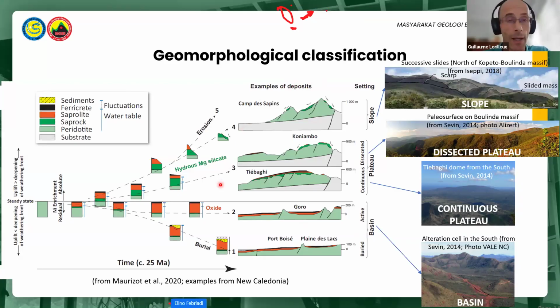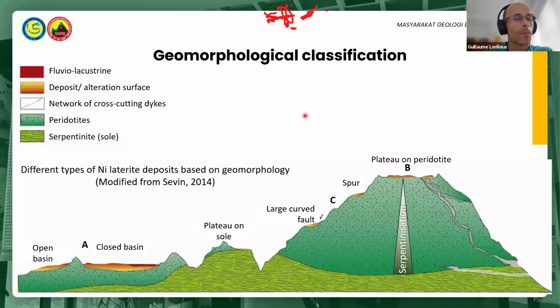The plateau deposits are topographically inverted former basins. Uplift increases from continuous plateau to the slope deposits. As the level of uplift increases, erosion also increases, leading to truncated laterite sequences and thinner limonite relative to saprolite. The importance of slope ruptures increases in dissected plateau and slope types and is associated with the development of deposits on the flanks of the massif. This is a different illustration of the geomorphological deposit types from Sevin and can be simplified into the same categorization: basin, plateau, and slope.